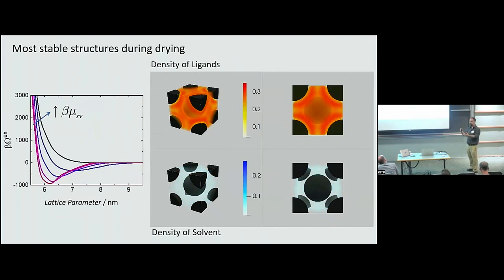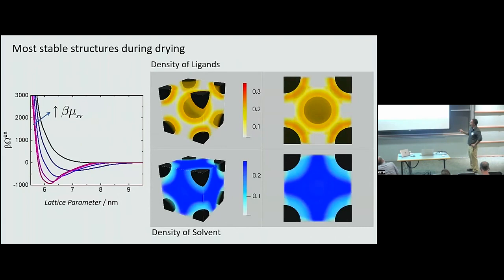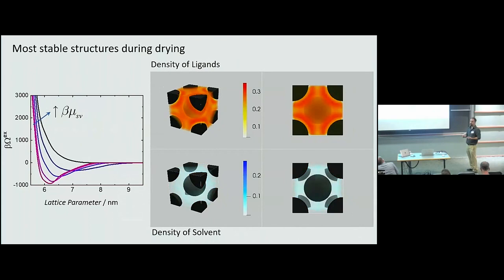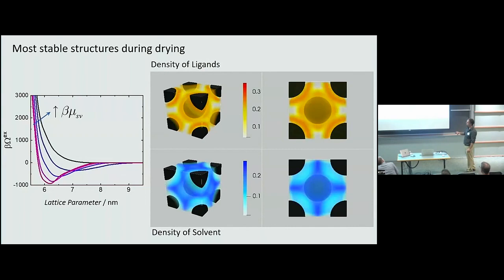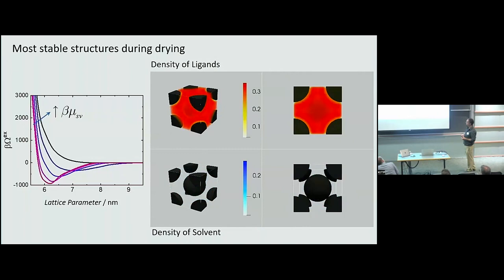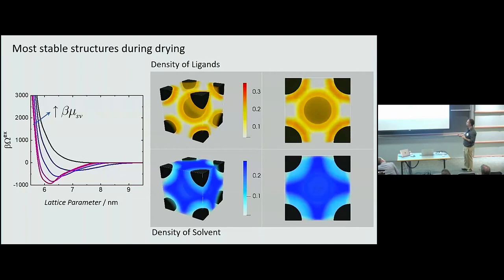So the thermodynamical information looks like that. We have in this plot the excess free energy as a function of the lattice parameter. And each of these curves corresponds to a different value of the chemical potential of the solvent. So when the chemical potential of the solvent is very small, you have almost no solvent in the system, and you have this very strong minimum, about 1000 kBT for the unit cell. So basically, this is the dry superlattice. The attraction is very strong.